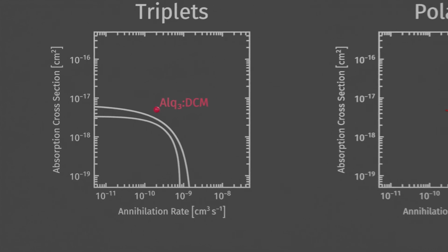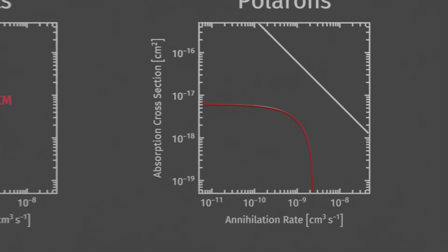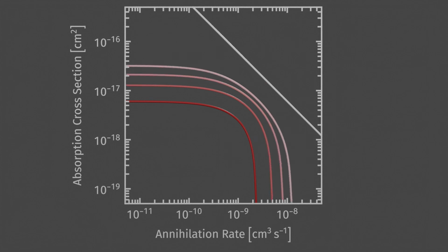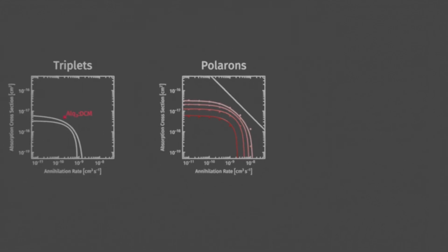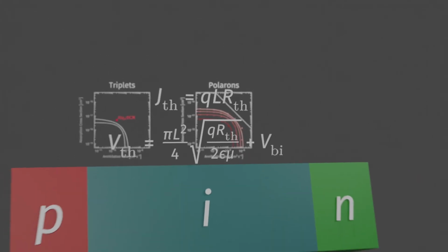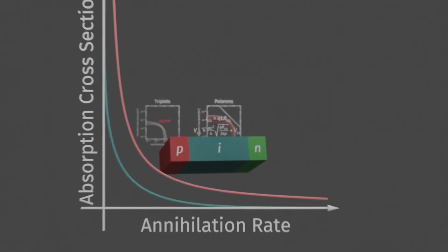Shifting over to polarons, the band between doubling your threshold and outright forbidding it is less aggressive. But if you consider 4, 8, or 16 times higher thresholds, it really doesn't make polarons that much easier to deal with. Drift diffusion simulations validate the approximations used earlier, particularly when polarons have any noticeable effect on threshold. Understanding that lasing from organic semiconductors is driven by bipolar space charge limited current gives you the basic relationships needed for designing devices and the speeds they need to operate at, but it can also tell you if a particular organic material is even capable of making a laser diode.